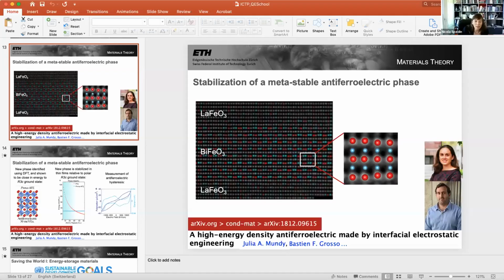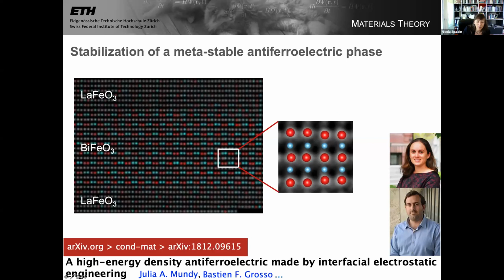This particular phase, the one that we looked at, is not very strain dependent. The experiment has not been done, but this has only been grown on lanthanum ferrite, which has a rather similar lattice constant, and a couple of other materials with similar lattice constants. But computationally, Bastien looked at the strain dependence, and he found that over a reasonable range of strain, it doesn't change its relative energy a lot. So with this phase, we don't really want to modify it anymore. We're quite excited to have it as it is, and it's fairly robust to moderate changes of strain. But that's absolutely a very good point.